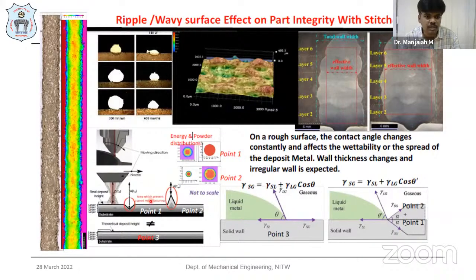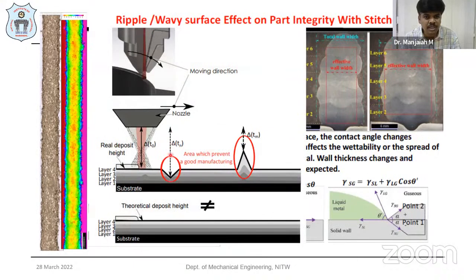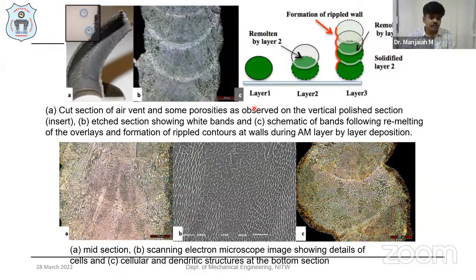In such cases, if you see these things exaggerated, these kinds of variations will be there. That is going to affect the offset distance, the focal point where the laser and the powder are interacting. That may vary because of these kinds of defects. That will definitely affect the quality as well as the wettability characteristics. And we have done some analysis in terms of mechanical as well as microstructural analysis. We have correlated how layer melting and remelting take place and the formation of the stair step for the rippled walls from the end layers.